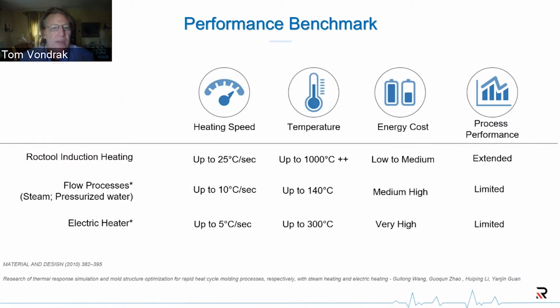Let's compare that to some of the other processes out there. There are flow processes. Now, I don't want this to come off as if we don't use flow processes as well. We actually use flow processes to cool our tools. The thing you should understand about flow processes is they are limited by the thermal conductivity of the tool steel that you're working with. And really the maximum amount of temperature change you can see is up to 10 degrees centigrade per second with a flow process. Clearly, for heating, Roctool can be 2.5 times faster than that.